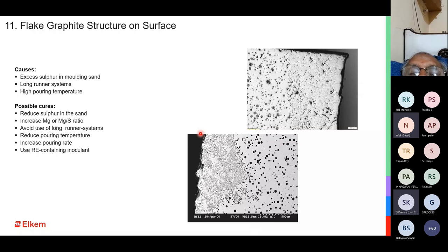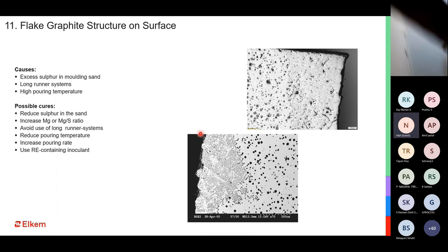Shall be more than 3, okay? Correct, right? Shall be more than 3. Yeah, generally, yes. But for example, if you are having 0.02 sulfur, you cannot have 0.06 magnesium. So in that case, this thumb rule does not apply.